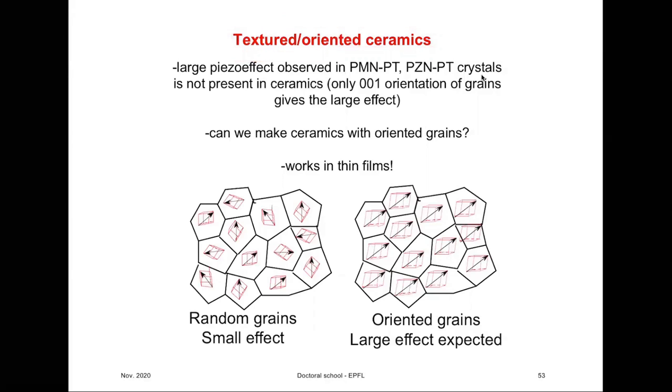Now you remember when we discussed symmetry of piezoelectric materials, we said that if you have a polycrystalline material with randomly oriented grains, then the only way to have piezoelectricity is having this polycrystalline material made of a ferroelectric, and then by applying electric field, we can reorient domains, polarization vectors in that material along the field and break the spherical symmetry, get conical symmetry, and induce piezoelectric effect.